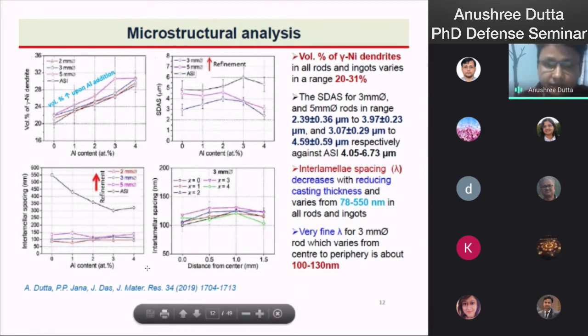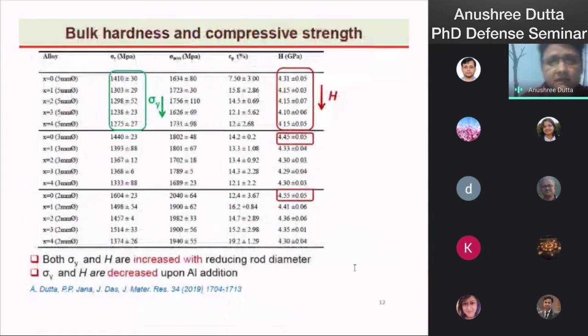Interlamellar spacing for the 3 millimeter diameter rod, from center to periphery, varies from 100 to 130 nanometers. As I measured, bulk hardness and compressive strength increase substantially in the smaller cast diameter rods, whereas there is a small decrease of bulk hardness and compressive strength in aluminum containing composites.